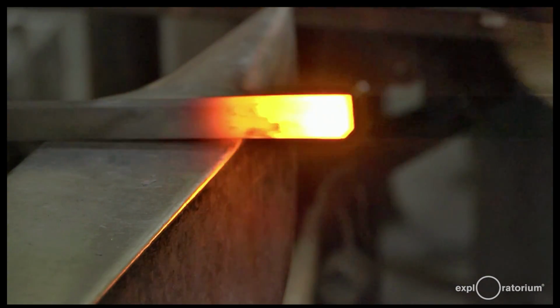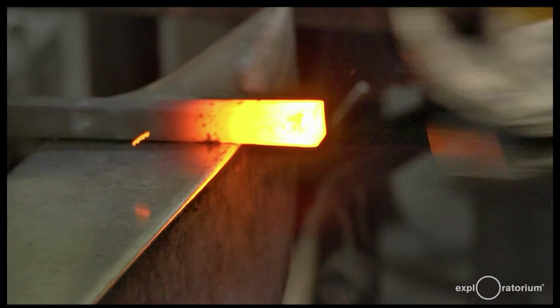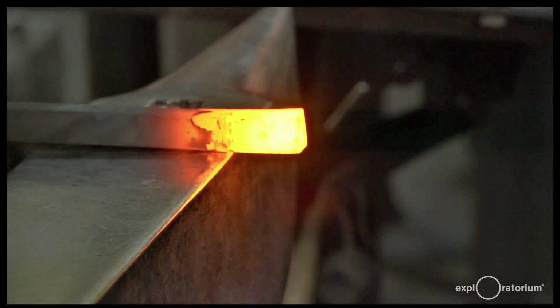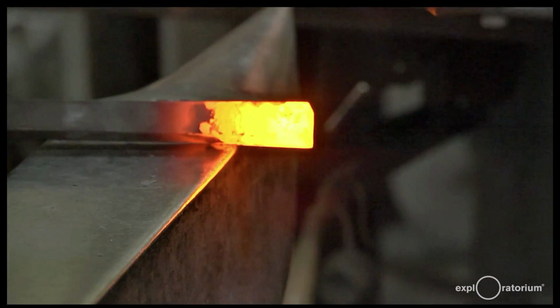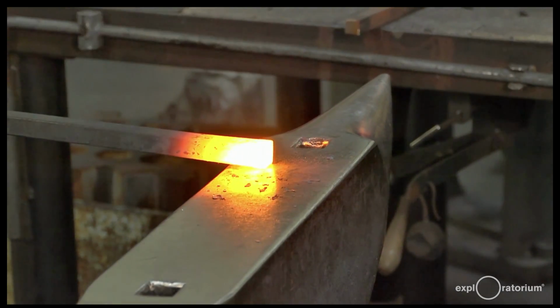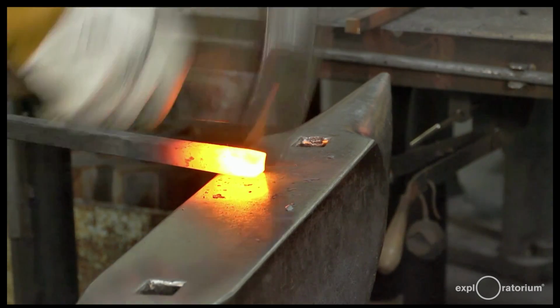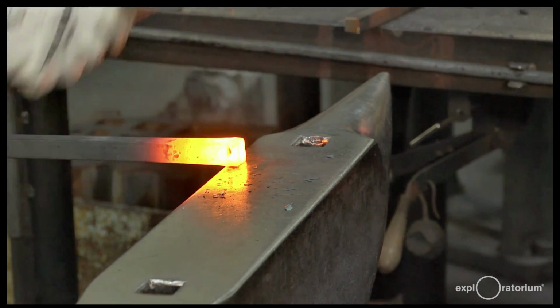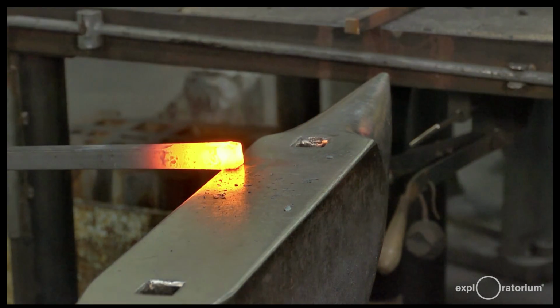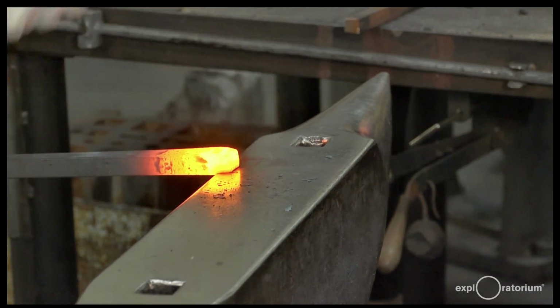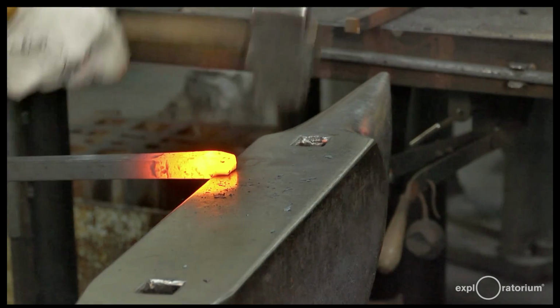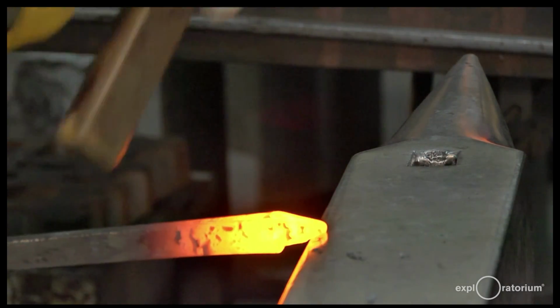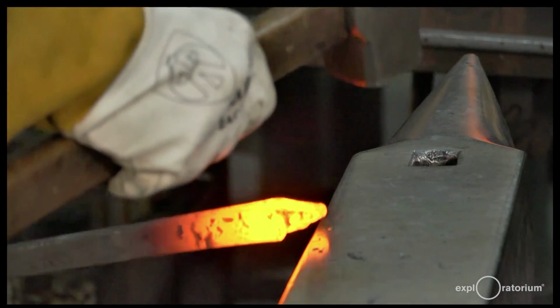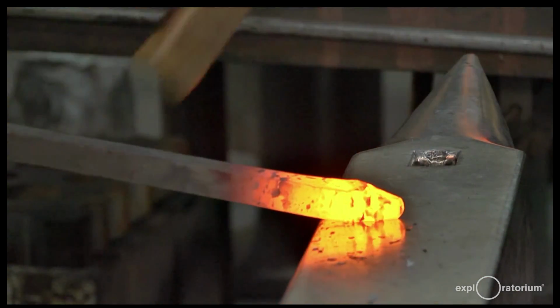You can't just lay 2 square bars together and weld them. You have to shape the ends in preparation for the weld in a process that's called scarfing. And prior to that, I'm doing what's called upsetting the iron, making it a little thicker, in preparation for the later hammering down of the metal during the weld. This is the beginning of the scarfing process. I'll just let you watch that for a minute. So you can see I'm tapering the ends out thin. And you'll see in a second how that helps blend one piece of metal into the other.